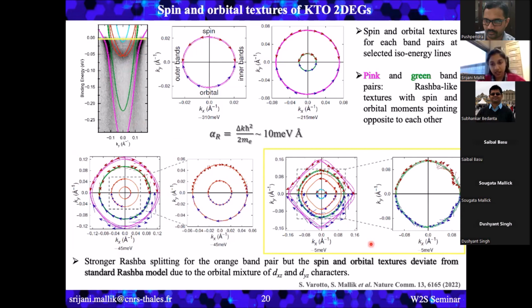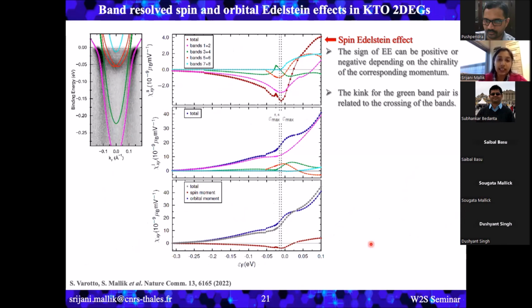And we start seeing, instead of a 2 pi rotation of spins in the full contour, 6 pi or 10 pi rotations. So everything got much more complicated. And in this scenario, we calculated the spin as well as the orbital Edelstein effects theoretically. And the top graph shows the spin Edelstein effect, where we can see that the sign of the Edelstein effect can be positive or negative depending on the corresponding momentum value.